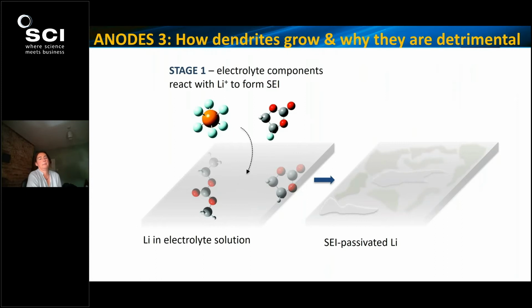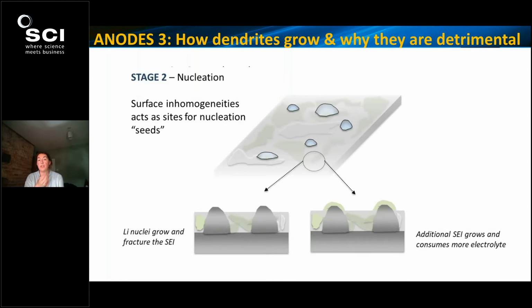And it's really interesting how they grow. So this very simplified schematic on the screen shows SEI growth on a lithium anode. Here you can see various electrolyte components that, when they enter into lower voltages, start to deposit these SEI passivation layers. And the SEI initiation is not always uniform. And so on an inhomogeneous surface, it can act as sites for nucleation where you get localized seeding of nuclei of plated lithium, which you can see at the bottom here, can actually then start to grow through the SEI layer. But the consequence of that is that it then adds more active surface to allow for more SEI to grow. So it's like a constant lithium consumption, if you like.